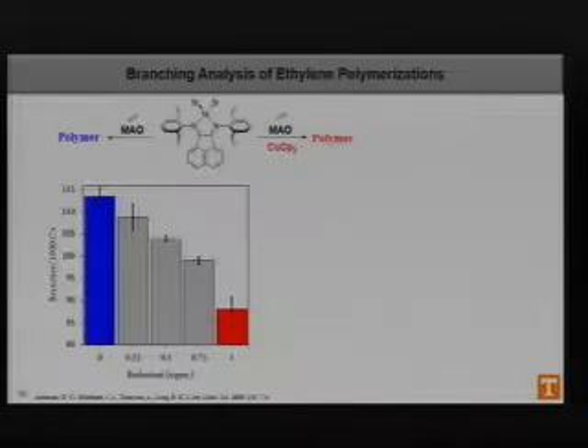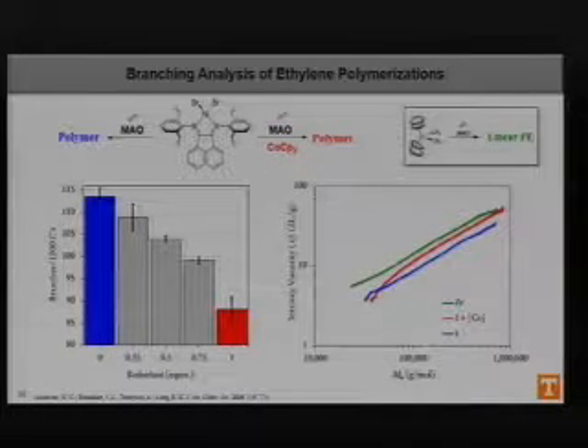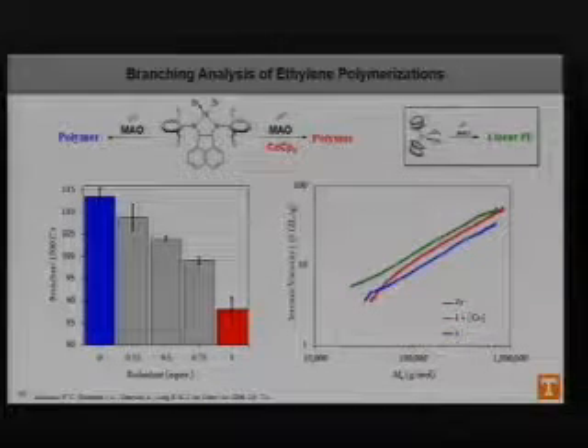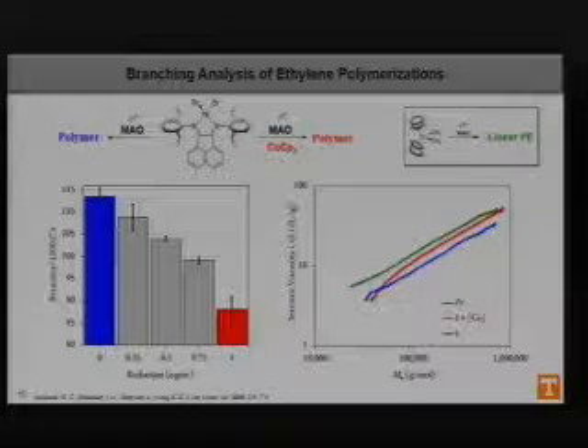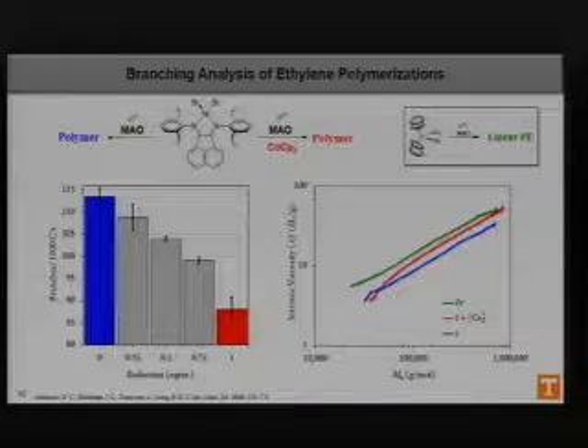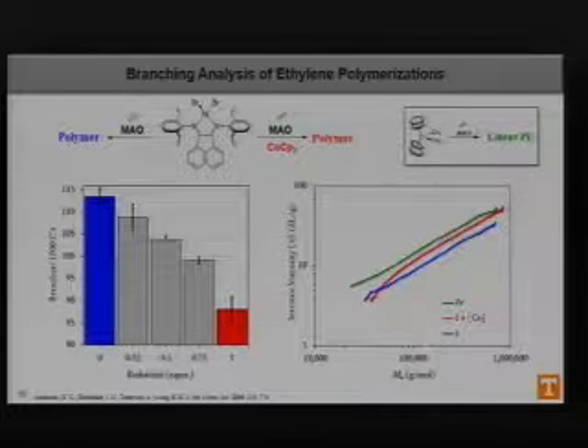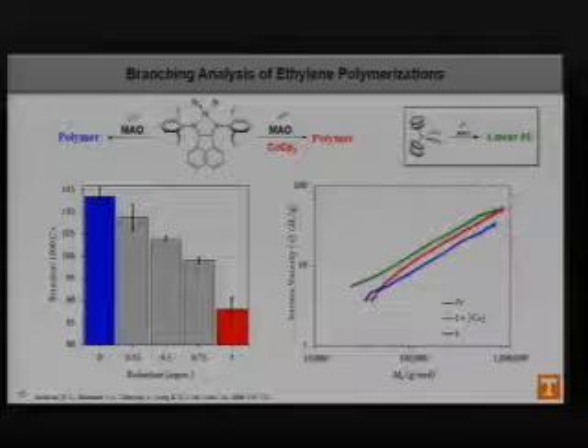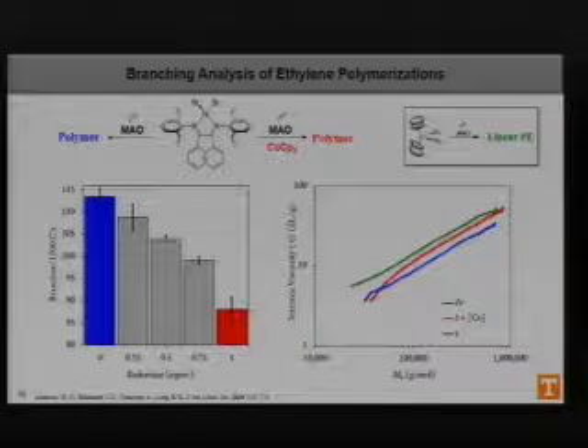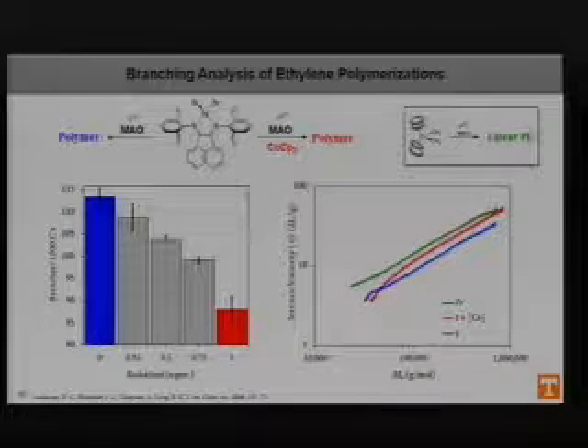So all in all, none of this really told us whether or not these two polymers were actually the same polymer. So we took proton NMRs of these polymers, and we found that as we increased the reductant concentration, this is the cobaltocene, the branches per thousand carbon began to significantly decrease in a corresponding manner, almost linear. It went from about 114 down to about 88 over here. When we took a GPC of both of these polymer samples and compared it to a known linear polyethylene standard, this is similar to the trace that I showed you before, where the furthest top left is the linear polyethylene sample. The standard catalyst is the blue sample, and then the polymer generated from our reduced species actually fell right in between the two.